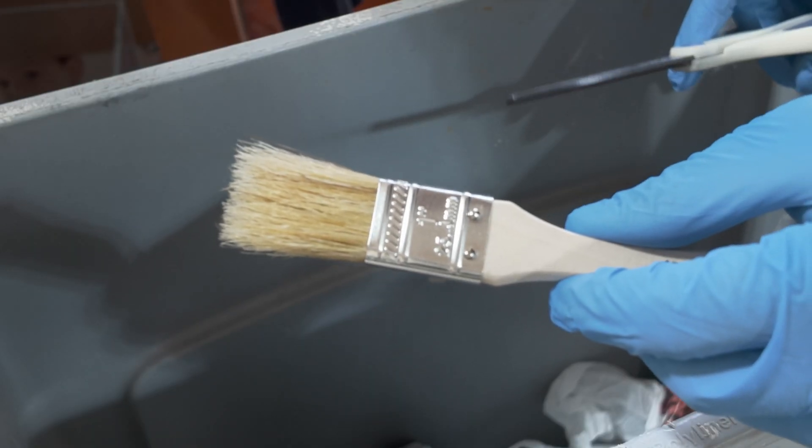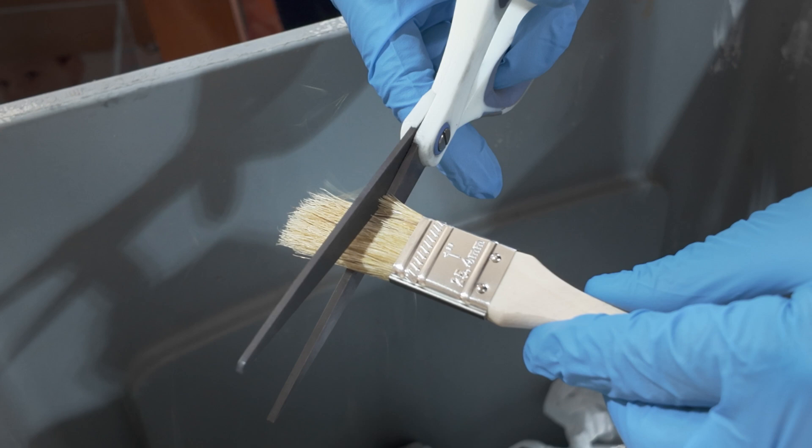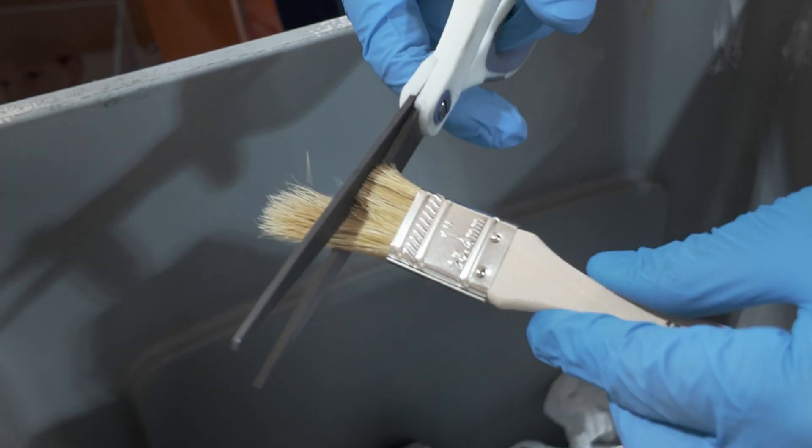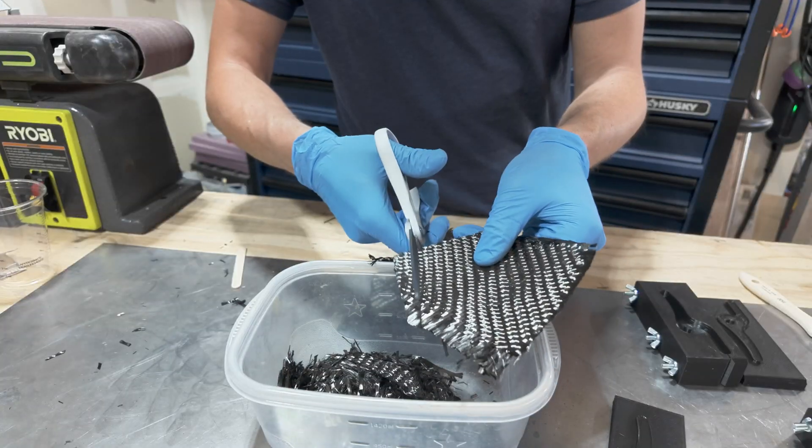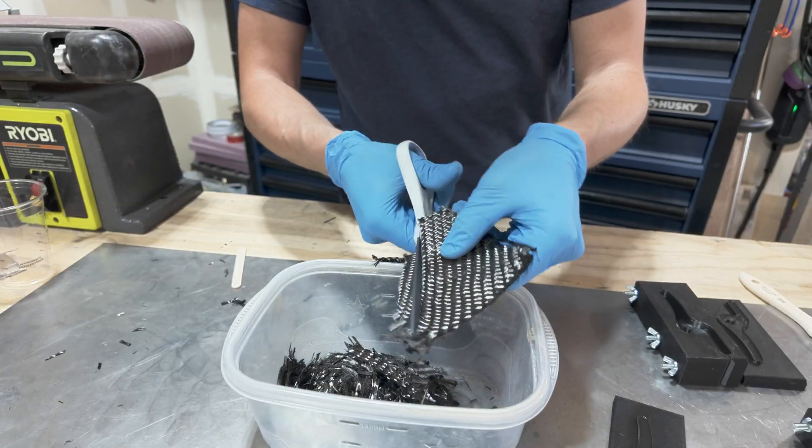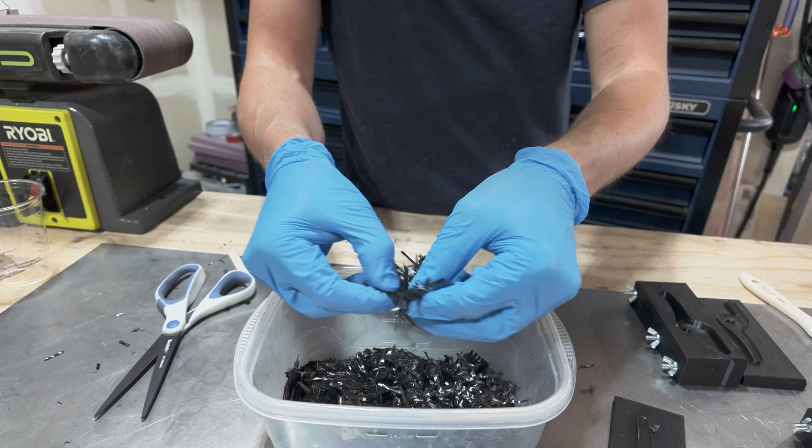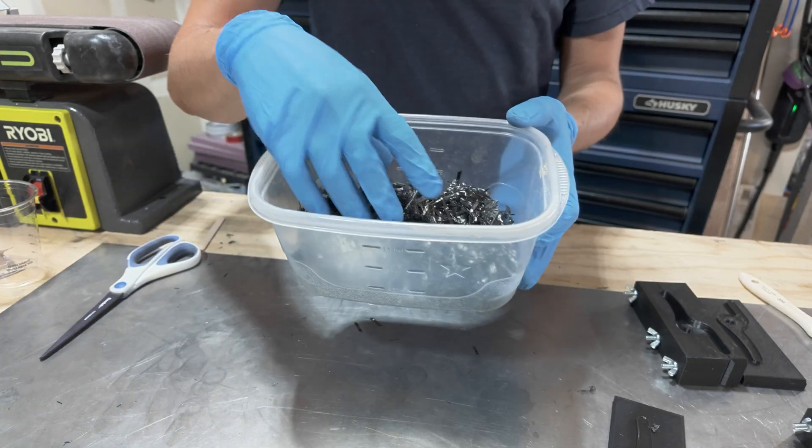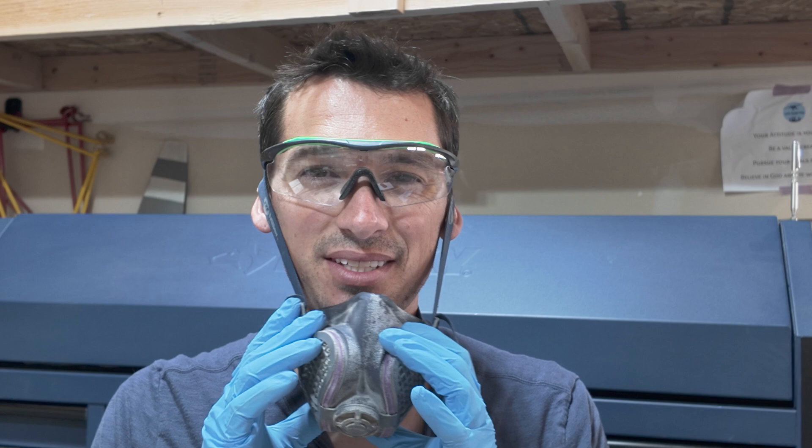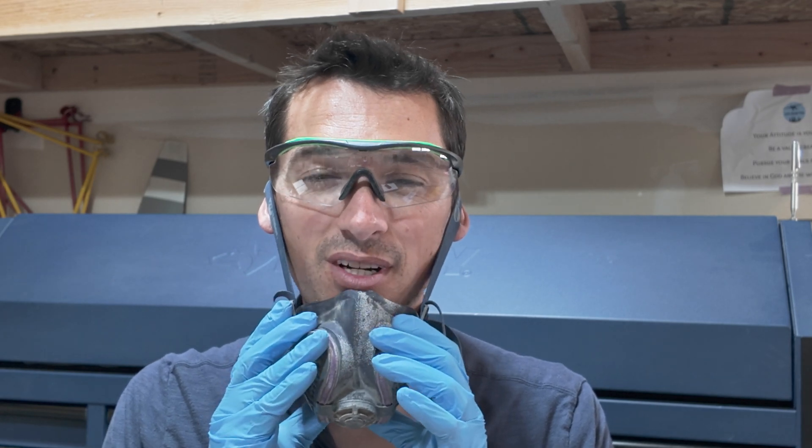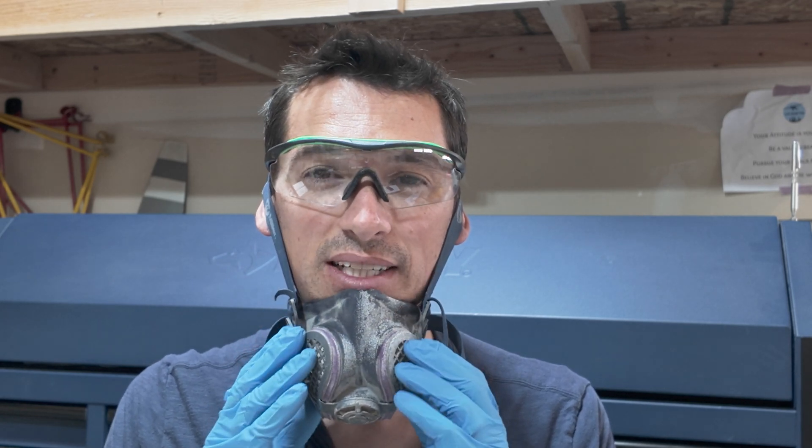Now the brush that I used for the wet up I actually like to trim it so that the bristles are nice and stiff. I had this leftover piece of carbon fiber that was just ready for a project. I chopped it all up at a 45 degree angle to make my carbon fiber tow making sure there were no pieces longer than 15 millimeters. All right be sure to wear safety gear while doing this. I always wear safety glasses, gloves, and a respirator. This is a nice compact one that I use. It actually fits under my welding helmet which is great and so just protect yourself as you work on these projects.